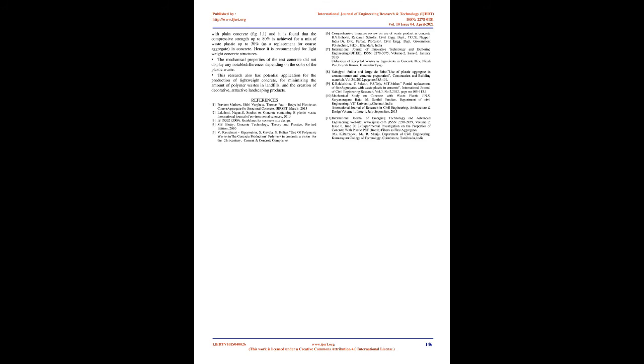Conclusions: The experimental results have shown the use of waste plastic material in making concrete or mortar can provide an alternative solution to minimize the environmental impact due to unscientific disposal of waste plastic. The properties of concrete containing various percentages of plastic — 0%, 10%, 20%, and 30% — were tested for its physical properties and compressive strength. The waste plastic used for experiments is of LDPE (low-density polyethylene), 5 to 7 mm size, and specific gravity of waste plastic is found to be 0.92. The compressive strength of test concrete is compared with plain concrete (FIG 1.1), and it is found that the compressive strength up to 80% is achieved for a mix of waste plastic up to 30% as a replacement for coarse aggregate in concrete. Hence it is recommended for lightweight concrete structures.